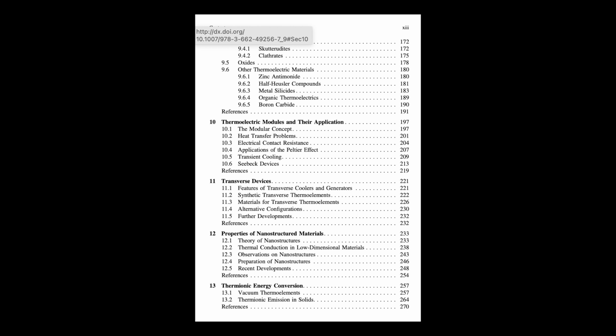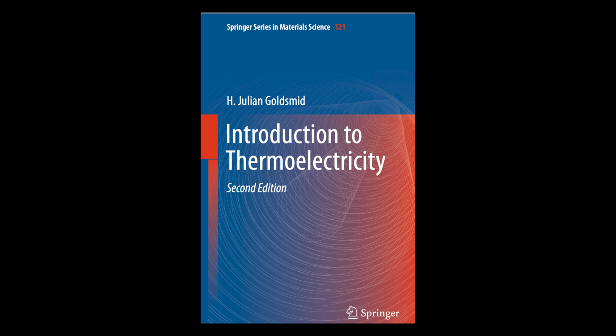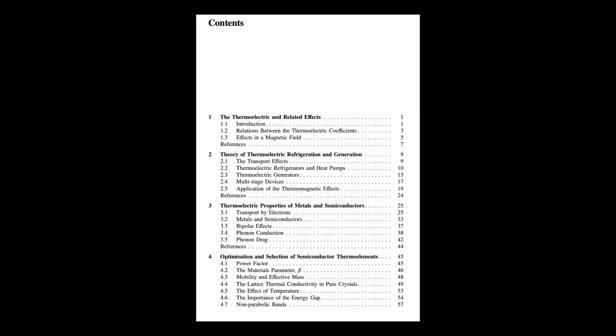And it's getting more interest now for power generation from low-grade heat. Absolutely. There's just so much waste heat out there from industry, cars, electronics, often at relatively low temperatures. Bismuth telluride alloys work pretty well in that low to moderate range, say up to maybe 200 degrees C or so. So they're really well suited for converting that otherwise wasted heat directly into electricity. Huge potential for energy saving, environmental benefits. Maybe not for super hot sources, but for tapping into lower temp waste heat, or even things like geothermal or ocean thermal gradients, they're a key technology. Great overview of the Bi-Te story.